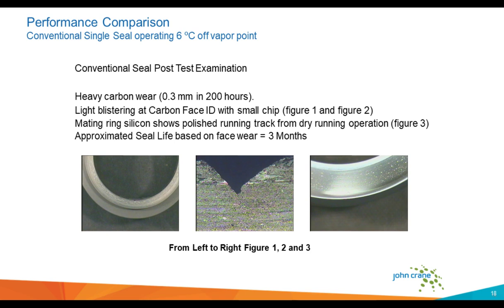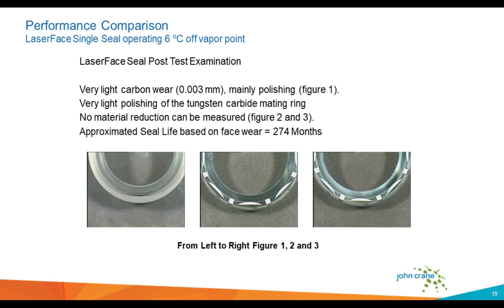In a conventional seal, we noticed that there was 0.3 millimeter of heavy carbon wear in 200 hours. Light blister at the carbon face is shown in slides 1 and 2, and a small chip, which is magnified, on the ID of the carbon face. The mating ring shows a polished running track from dry running operation due to the vaporization of the liquid again, and approximate seal life based on the face wear was about 3 months.